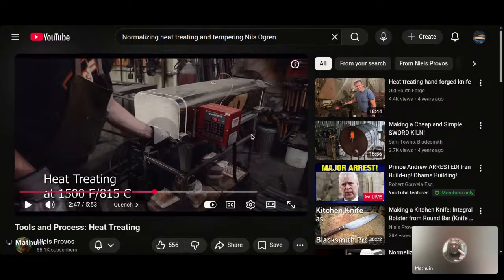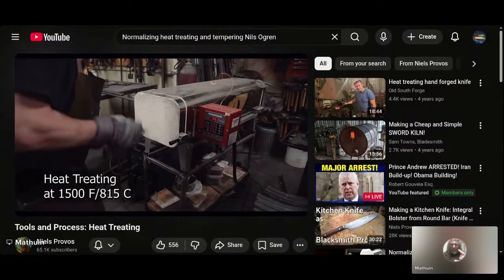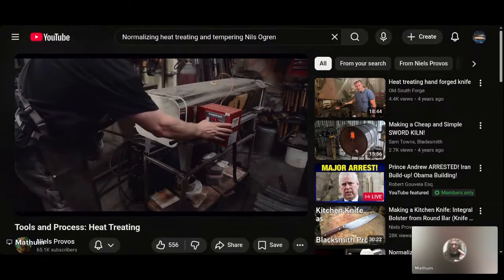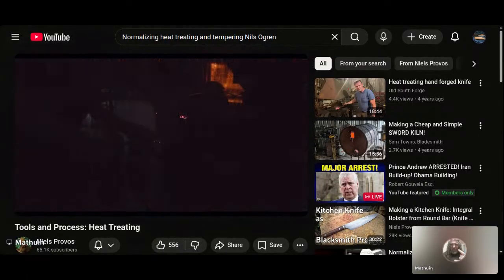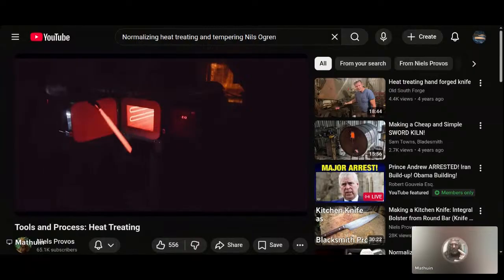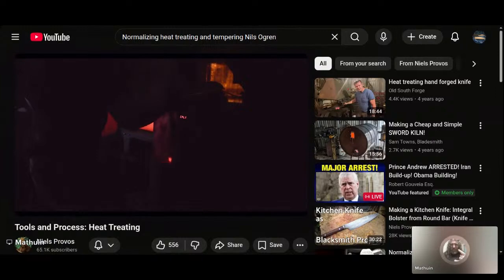That's what matters. When quenching in oil, I always wear full face protection. If the oil gets too hot, it can rapidly ignite and flames can spurt up into your face. Before quenching the blade, I quickly check it with a magnet to verify that it is no longer magnetic. When I insert the blade, I also move it up and down vertically to prevent a rapid transition of hardness